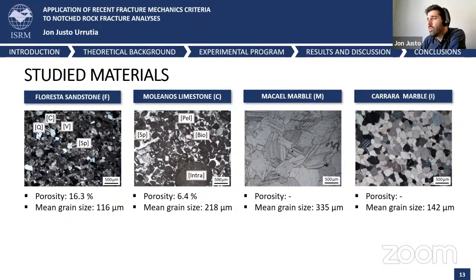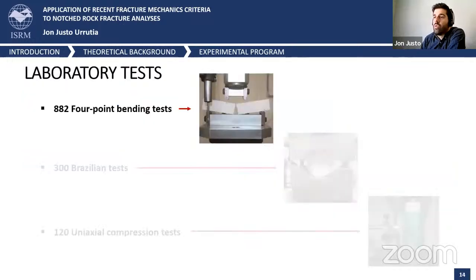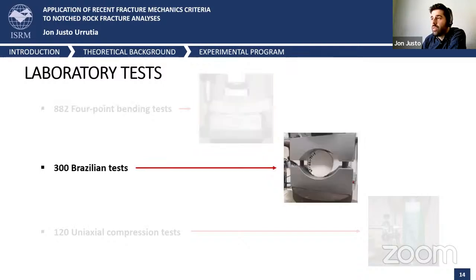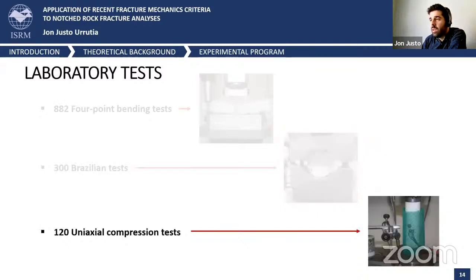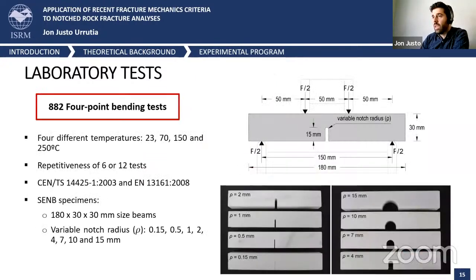From a microstructural point of view, the main difference between these two marbles is the grain size, the crystal size, which is relatively larger in the case of the Macael marble. For the characterization of the required parameters, almost 900 4-point bending tests have been performed, which provide pure mode 1 loading conditions. 300 Brazilian tests have been performed, and finally 120 uniaxial compression tests with strain measurements.